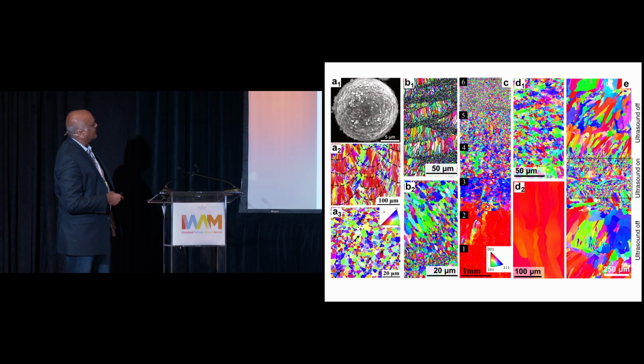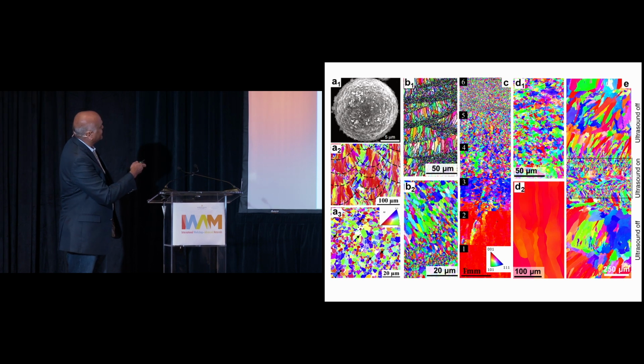You can see there are a lot of features, for example, if you add particles to this powder—nucleation agents, carbides and ceramic particles—then you can actually force what we call the columnar to equiaxed transition. Let me illustrate that with this particular example.